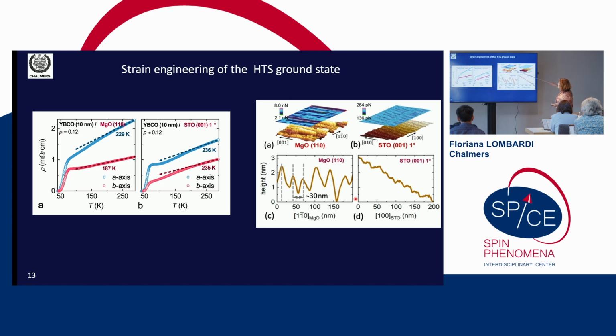But what is surprising here is that if you take peak force measurements, you get a very different contrast across the samples, and you have this dark region at the tip of the substrate, where you have tips of the substrate on the film. And what we believe is that here you have uncoordinated atoms with dangling bonds, and they strongly bond with the YBCO, making different materials. You could get this also on strontium titanate, but these regions here are very tiny, corresponding only to where you have uncoordinated atoms in the substrate.